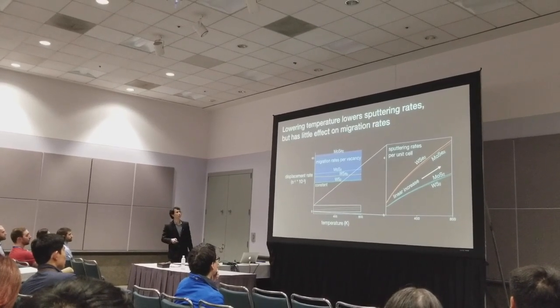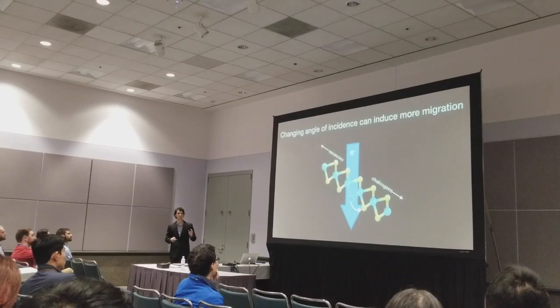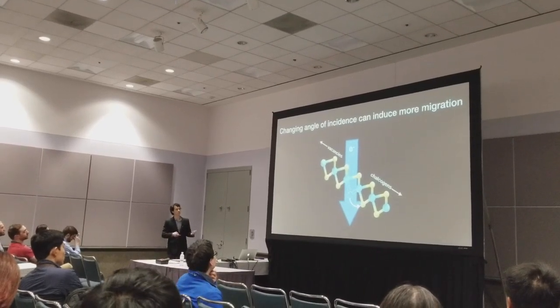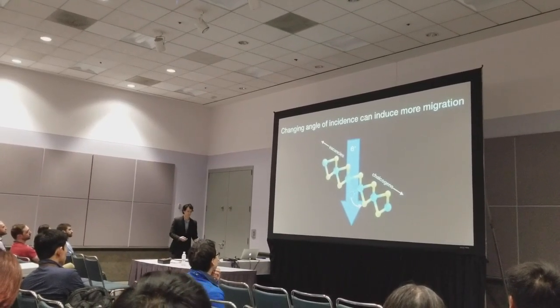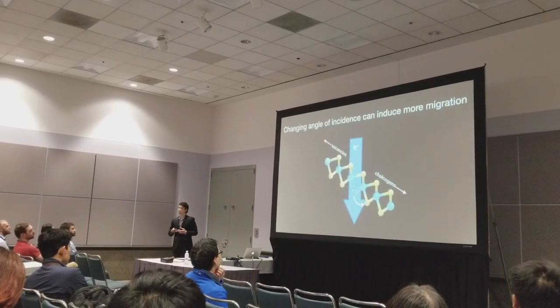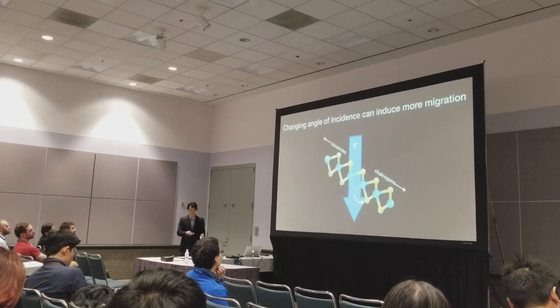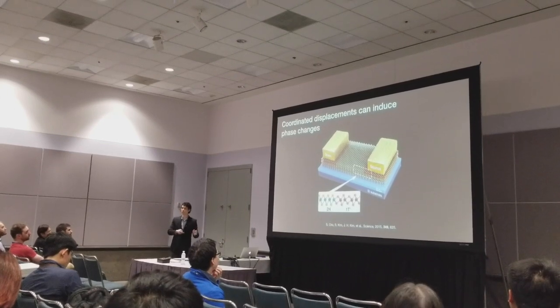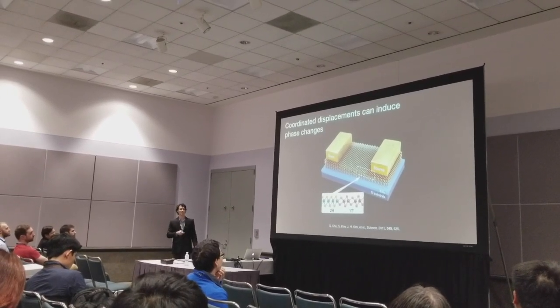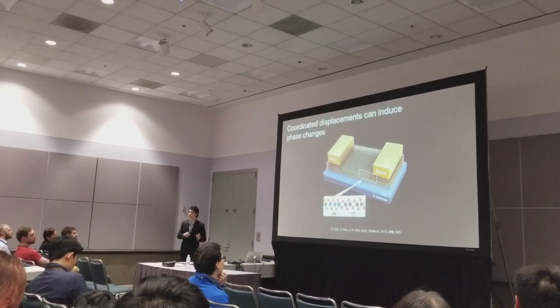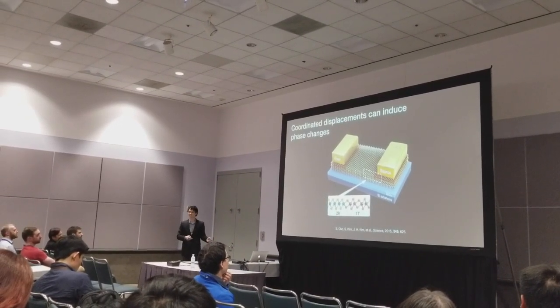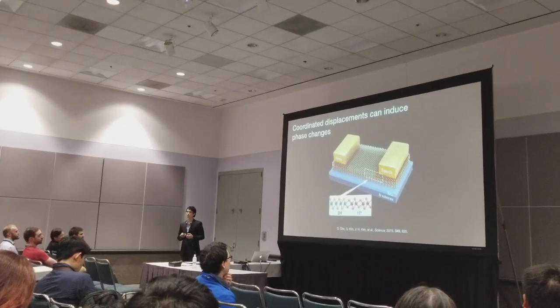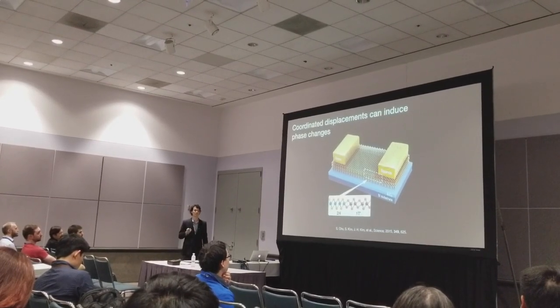So how do we use this? One thing we can play with is the angle of incidence of the irradiation — this way we can literally tilt rates in favor of migrations. A net flow of vacancies in one direction should lead to pristine material in the other direction. Additionally, a set of coordinated displacements could lead to a local phase transition within a material. This is particularly interesting for TMDs, for which the 1T and 1T-prime phases are metallic compared to the semiconducting 2H phase. This allows for interfaces within a material where electrical contacts are truly ohmic, with huge applications in device engineering.